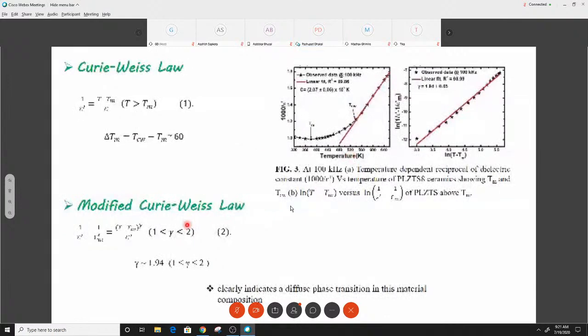Further, we analyze, quantifying the relaxor behavior of the material with the modified Curie-Weiss law, and we got the value of gamma equal to 1.94. When the gamma value is between 1 and 2, it shows the relaxor behavior of the material. When gamma is equal to 1, it shows the ferroelectric behavior of the material. So in this case, our grown material has a diffuse phase transition.